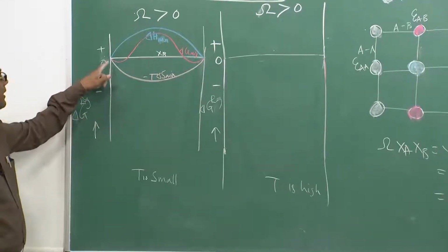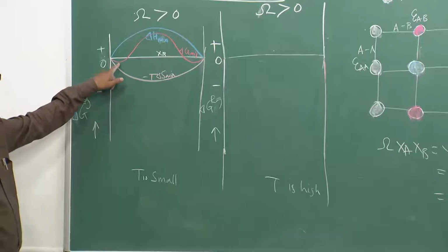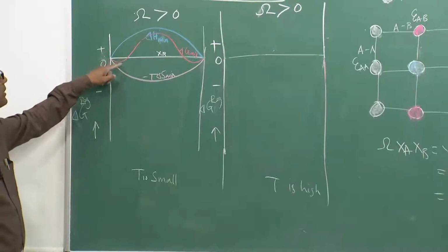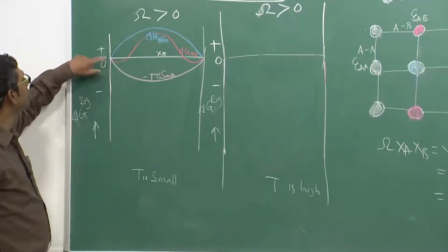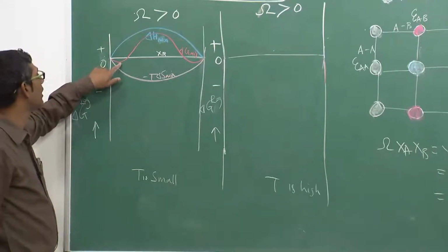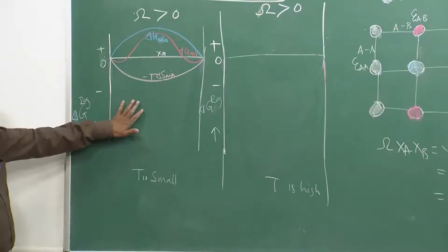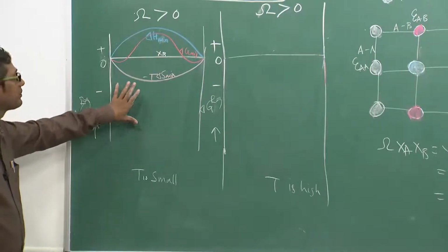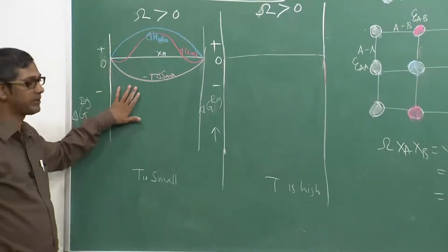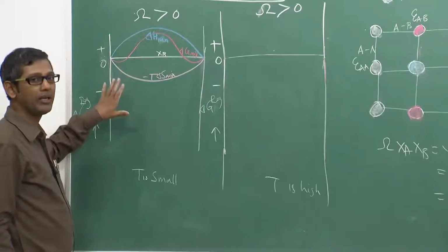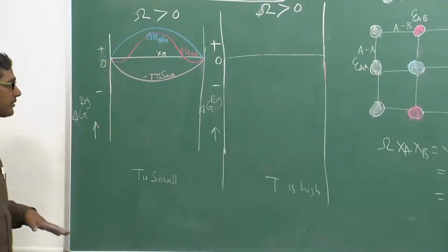So, that means delta G mix has an inflection point, because there was a downward slope and then an upward slope, and when these two slopes match at a certain point, it will have an inflection point here, and an inflection point there. Please remember this plot, because this plot is very important for many phase transformations. This one will help us in understanding many phase transformations.